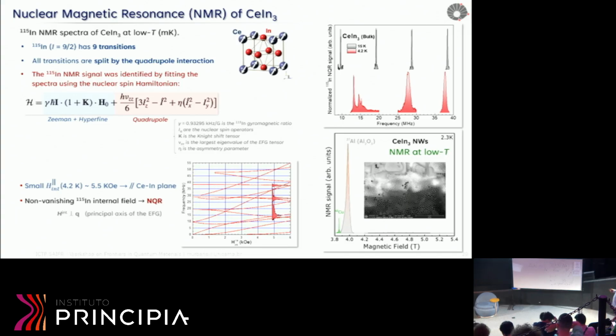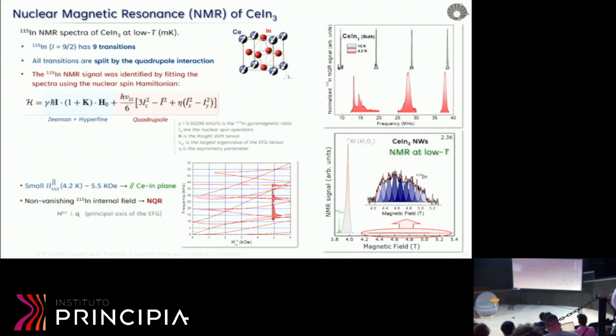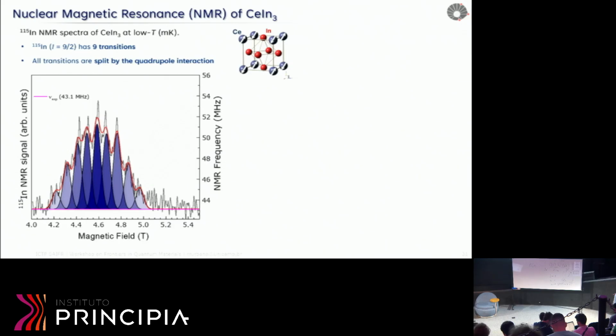And what we see here, here's the copper signal from the solenoid, the RF coil. Here's the aluminum signal from the alumina template. And with very good faith, our indium spectra is here. That's kind of frustrating because the signal is very weak. The density of wires inside the template is low, but we could see some signal. We can fit it and explain, as I'm going to say real quick here.